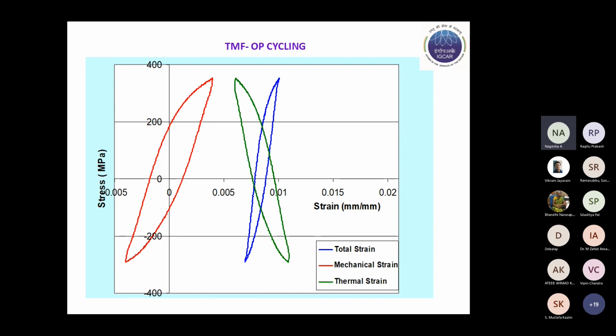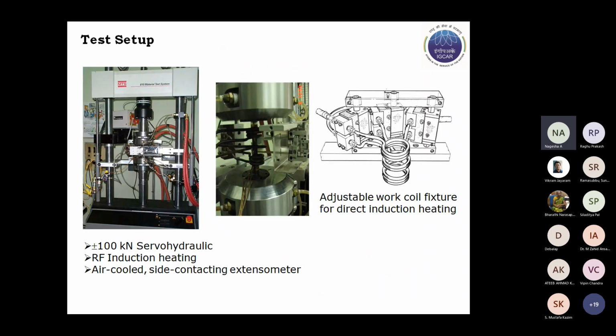So in the case of OP, this is a typical hysteresis loop wherein you see that the temperature and mechanical strain are completely out of phase with each other, and the total strain is also given. A typical test setup that was used. I'll just give a brief outline about some of our tests that we have carried out on ferritic and austenitic stainless steel, including the weld joints also. This is the test setup that was used.